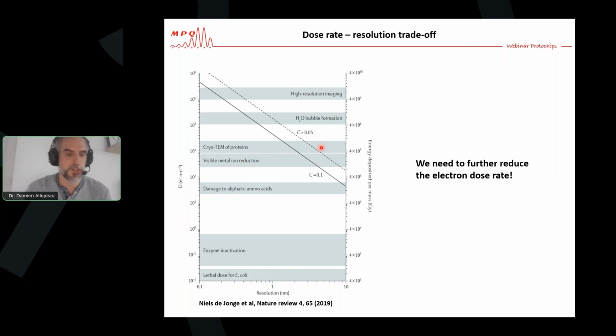And you see, obviously, if you reduce the dose rate, you reduce the resolution. But this graphic also shows you all the beam-induced phenomena that can occur during your experiment. So if you work at high resolution, you have a very high dose rate, but above 10,000 electrons per nanometer square, you start having hydrogen bubble formation in water.